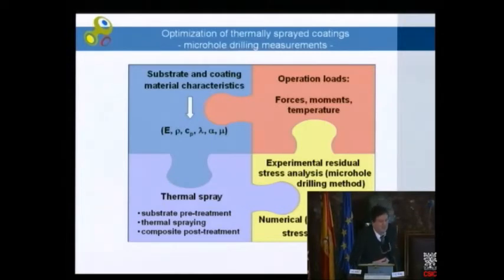It will start at the beginning at room temperature, not as cold as we have it in Northern Europe just now, but then it will run up to a temperature close to the turbocharger, 600, 700 degrees C, surface temperatures. That means we have also to think about the operational load stresses, the mechanical ones, and the thermal stresses that occur in the final mechanical system. And last but not least, the modeling and simulation is now the essential tool to understand, to calculate, to estimate the interaction between the stresses that are occurring from our process and the interaction with the operational load stresses.